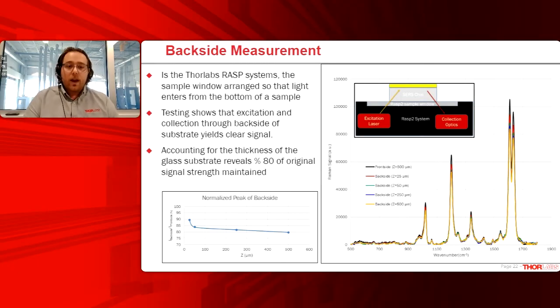The next characterization we ran was backside measurements. There are some applications where the excitation laser and the collection optics can't be in the same space as the active SERS area. And I'll talk about one of those in our application section. But what was nice about this test is our RASP2 Raman spectrometer has this very setup. The excitation laser and the collection optics are hidden behind a window, and you have to place your SERS substrate on top of a sample window. So we ran some tests, and what we found was that even when we account for the thickness of the glass substrate, we can still maintain 80% of the signal intensity compared to a front side measurement. So for some applications, this is a very useful method to perform remote sensing.